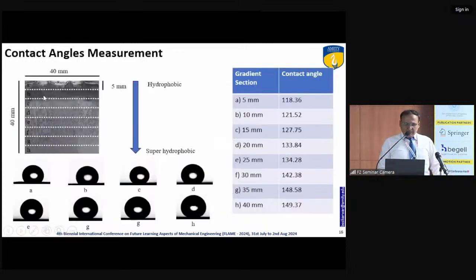And when we measure the contact angle from this unidirectional hydrophobic to superhydrophobic surface for 40 mm surface, every 5 mm distance, these are the contact angles we can get here. So 5 mm we get a 118, then 10 mm we can get a 121, then 15 mm we get a 127, 20 mm we get a 130, 25. All these contact angles we can get here.